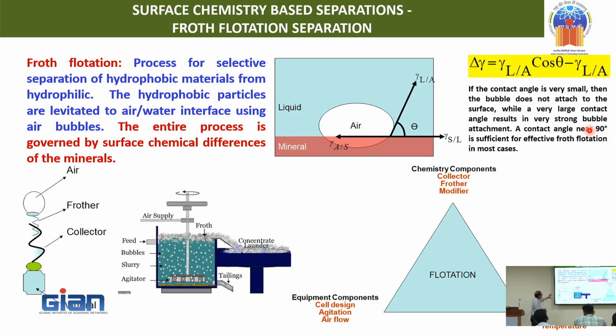So you can see here physically, this is the mineral and this is the collector. This particular part is a hydrophobic chain and this is the hydrophilic chain. This has chemical affinity to the surface of the mineral, maybe to the metal ion present in it or to whatever is disposed on the surface. So once it is adsorbed, you introduce the air bubbles. But air bubbles as such also will not be able to bond with the collector molecules because there will be some residence time, that is called induction time. The induction time should be so planned that the collision is fruitful.